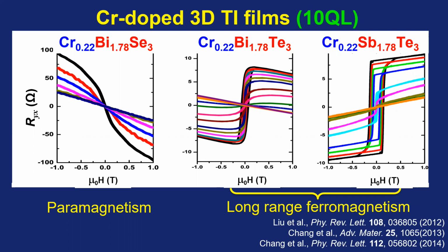We forget this material. For the chromium doped bismuth telluride and antimony telluride, we can see the anomalous Hall effect is much more square. So in this one, the ferromagnetic order is better. So from the transport data, we choose the chromium doped antimony telluride as the best material for the realization of the quantum anomalous Hall effect. We choose this material as the parent material for realizing the quantum anomalous Hall effect.